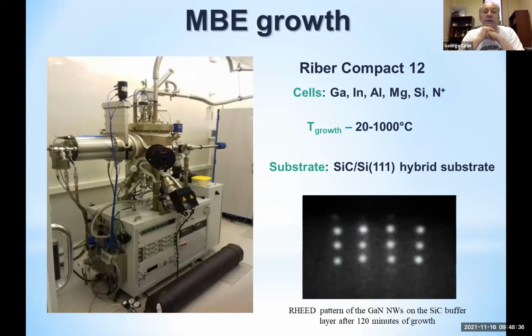For the growth of the nanowires, we are now using a small Riber compact MBE setup, which is equipped with metallic sources like gallium, aluminum, as well as doping sources like magnesium and silicon, and a plasma-assisted nitrogen source. We use different kinds of substrates, silicon carbide, and this stuff is nice from the point of view of basic research, but practically it cannot be used for production. But anyway, to see what the trends are, what the typical tendencies are, we may simply use this setup.